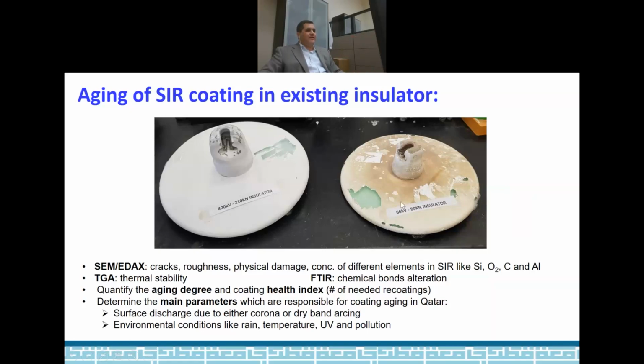You see, we scratch them and try to analyze what exactly happened to the commercial coating, and to understand how the environment in Qatar affects these kinds of coatings. Mainly, we look at SEM and EDAX to track the roughness, physical damage, and the concentration of different elements like silicon, oxygen, carbon, and aluminum over time under weathering conditions. Also the thermal stability after exposure to the Qatari environment, and FTIR to see if any chemical degradation happened to these coatings. Then we quantify the aging degree, what we call the coating health index. This helps companies like Karama to measure how many times they need to recoat these insulators in order for them to continue doing their function.